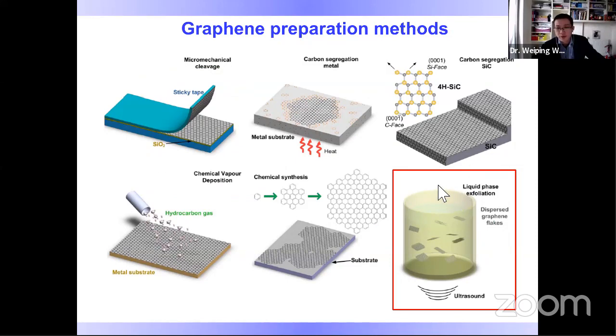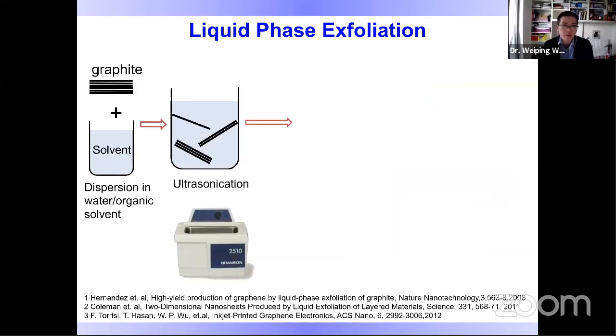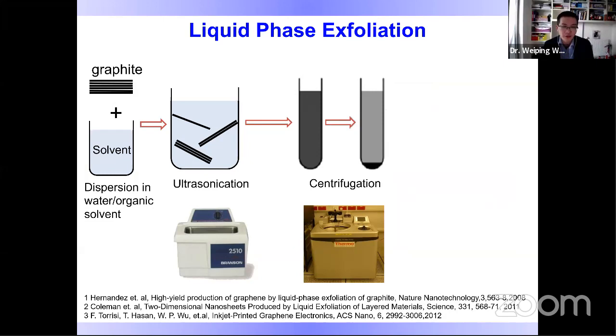So this slide summarizes the various methods to prepare graphene. One fundamental challenge is how to obtain high quality graphene at a low cost and high volume. The only choice tends to be chemical or liquid phase exfoliation. Here we use very low cost starting materials like graphite and solvent. Then we use bath sonication, which is the same facility used to wash glassware in the lab, and after mixing with the solvent and sonicating for 10 hours, we use a centrifuge to isolate the graphene from the unexfoliated multi-layer graphene flakes.